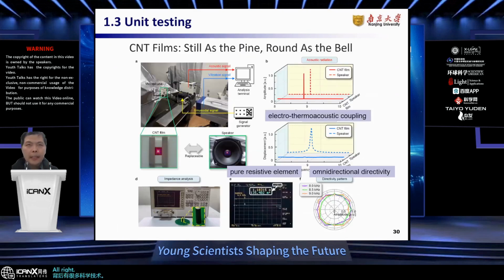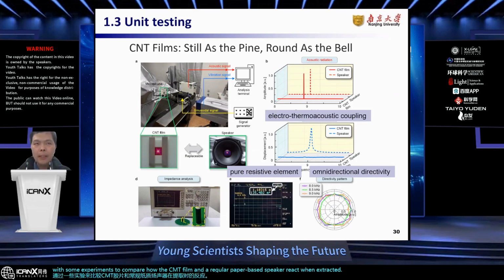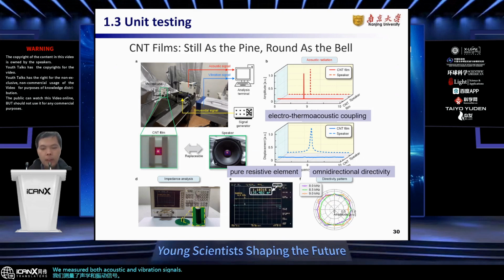All right, let's dive into the world of finite sonic crystals. First, we need to understand the CNT film a bit better. We did some experiments to compare how the CNT film and a regular paper cone speaker react when excited. Using a microphone and a laser vibrometer, we measured both the acoustic and vibration signals. You guess what? The acoustic pressure amplitudes were pretty much the same in both cases, but the CNT film hardly vibrated at all on its surface, while the paper speaker was shaking like crazy. This just goes to show that the CNT films create sounds through thermoacoustic coupling, not by traditional vibrations.